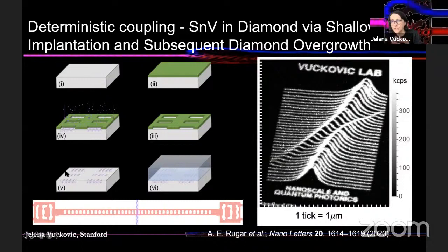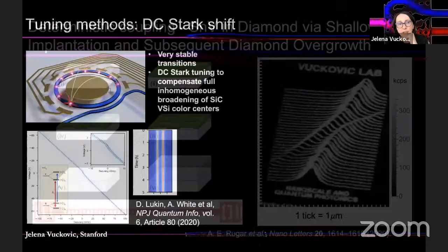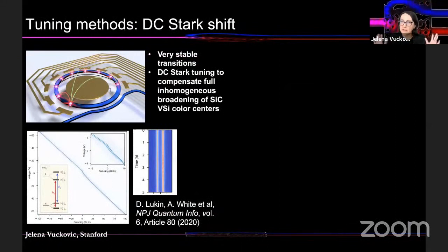But of course, if you do it at low energy, then your ions end up being shallow implanted, close to the surface. So you need to finish everything by growing high purity diamond on top. We've shown that this is possible, and we get the same quality of color centers, same quality of these spin qubits as people get in bulk environment, which is great. And we can actually incorporate them at desired positions, including the positions of my group logo, which is not really useful, but shows you that we can really control it. And of course, once you do it on a regular grid, then you can also align your photonic structures in the second level of lithography. And then for spectral control, we developed a variety of tuning techniques, but we're most excited about very simple Stark shifting, which means you put electrodes and then shift your color center transitions by some amount by DC Stark shift.